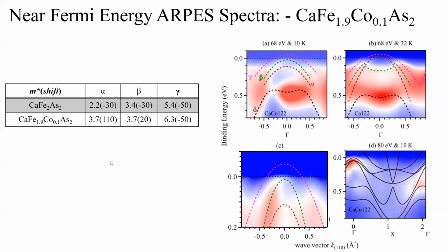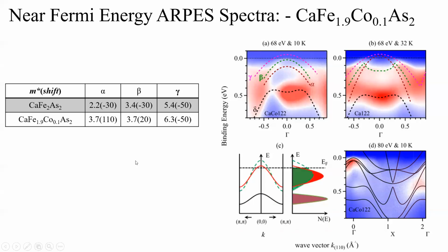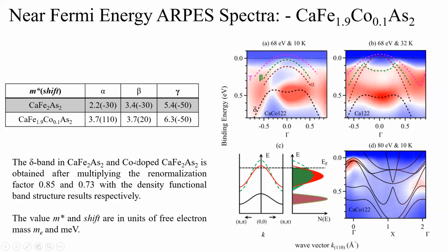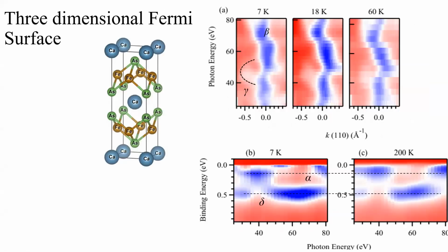So what we basically see is that with cobalt doping, we are not only doping electrons into the compound, we are also increasing a significant amount of correlation in the compound. And that's what I basically wanted to say from here. What else do we see? This is the Fermi surface mapping. The photon energy is, as I said.